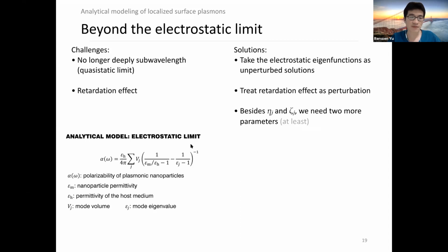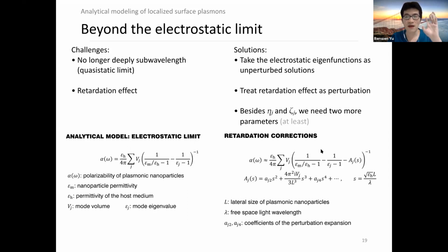Let me give you an example. Here is again the optical polarizability for noble metal-based three-dimensional structures, which can also be decomposed into a summation of the eigenmodes, where now V_j is the mode volume and epsilon_j is the mode eigenvalue, in the electrostatic limit. In order to solve the problem in the quasi-static limit, we need to take retardation corrections into account, which appear as this A_j term here, and this A_j term depends on S, the size parameter, defining how subwavelength our nanostructures are.